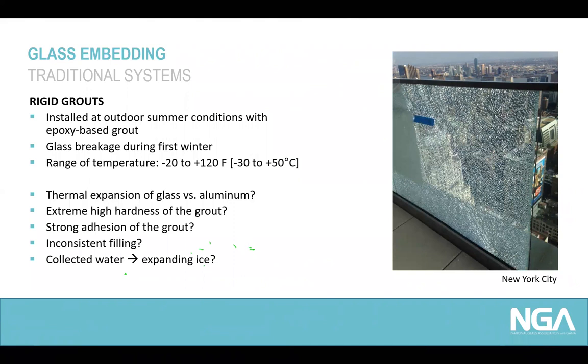That just underlines the different risks you have in an outdoor system, and you have to accommodate also the thermal expansion between glass and aluminium channel. Any rigid material would not be able to accommodate the dilatation between the two different materials. The extreme hardness of the grouting material can cause peak stress or even higher stress impacts on the glass unit. Epoxy-based grouts usually have a very strong adhesion to various substrates. So producing here a strong adhesion between the aluminium base shoe and the glass just increases the risk of constraint forces and additional stress, and the risk of breakage for the glass unit.